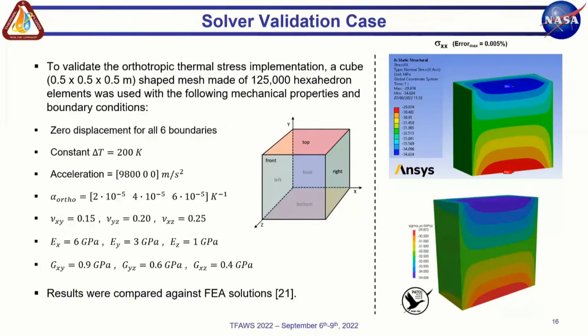This is a 3D validation case for the orthotropic stress analysis solver that includes thermal stresses. The model is just a cube-shaped structure made of 125,000 elements with the boundary conditions of zero displacement applied on all the boundaries, so the volume remains constant. And also the temperature of the body was increased by 200 Kelvin with respect to our reference temperature. And we applied a body acceleration of 9,800 meters per second squared in the x direction. So we also have some mechanical load in addition to the thermal stress.